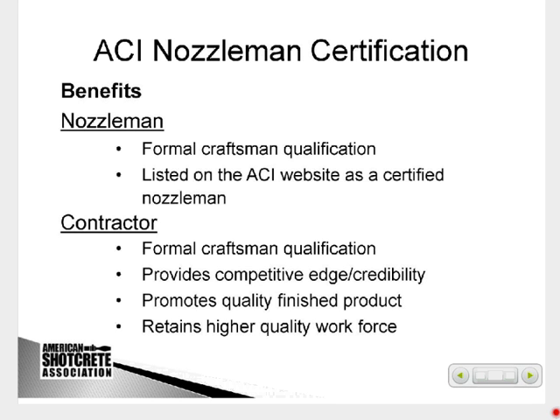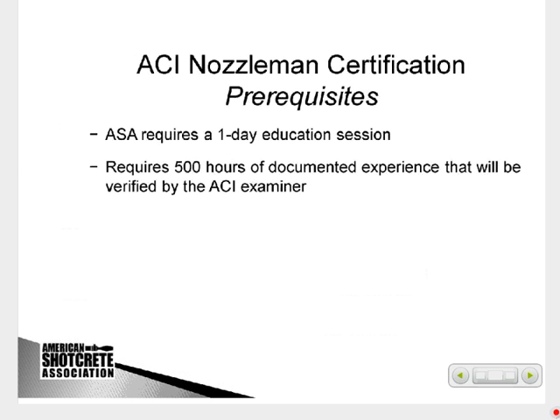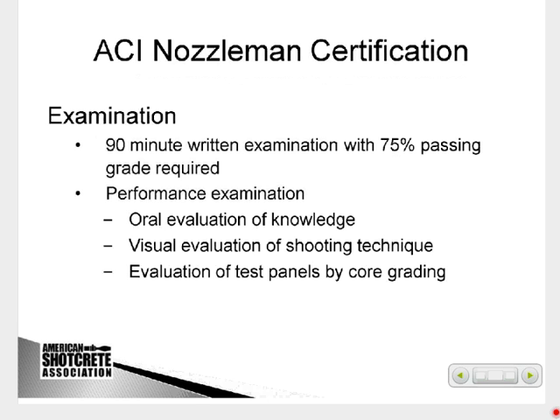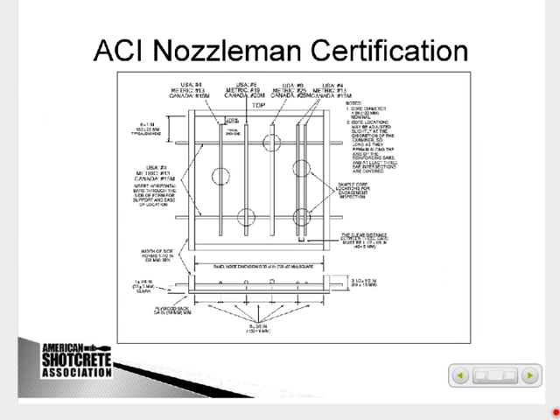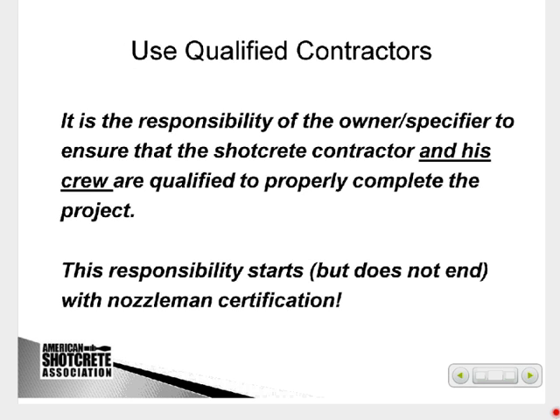We do have ACI Nozzleman Certification. This is a 5-year certification. They basically have to pass a written exam, with the ASA education session required that I mentioned before. They have to have 500 hours of documented shotcreting experience. And then they pass a 90-minute written exam. And then there's a performance exam where they actually shoot a panel that's 3.5 inches deep, 30 by 30, and shows different types of rebar. And they are graded. We basically core these and grade the cores on their ability to encase the rebar. And they can either pass or fail based on the cores.